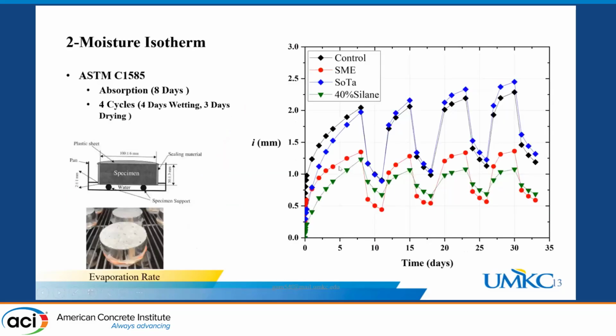The second thing we looked at is the moisture isotherm, for which we followed the procedure described by ASTM C1585 for 8 days. We have been working on evaporation rate using the sealers from previous research, which I presented at the last convention. We think evaporation must be considered because it affects the data. The evaporation rate procedure is similar to the absorption rate; the only thing is we flipped the sample and monitored them in the environmental chamber.